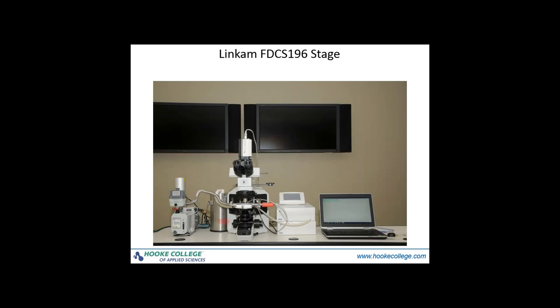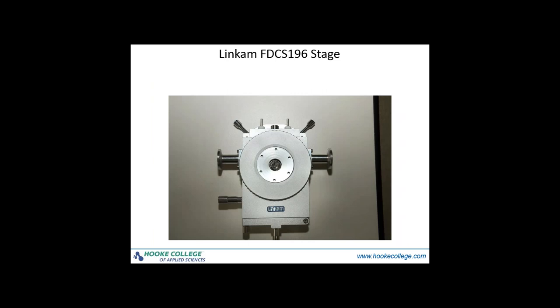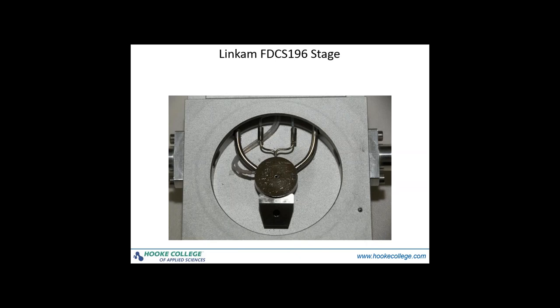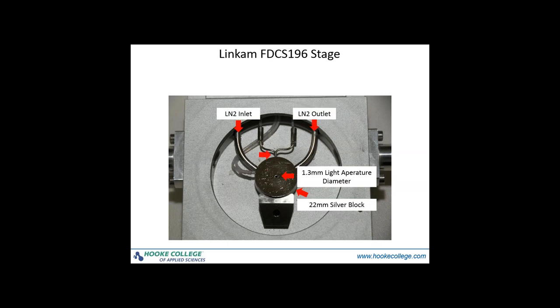Going on with the Linkam stage, this is the Linkam FDCS196 stage. So therefore, here we have our vacuum ports, we have our X manipulator, we have a Y manipulator so we can move our sample in any direction, we have our sample door lock. Once I remove the lid, we have a 22 millimeter silver block, we have a 1.3 millimeter light aperture. We have a liquid nitrogen inlet, liquid nitrogen outlet, we have our platinum resistor leads, and we have our thermocouple leads, and our sample ramp.